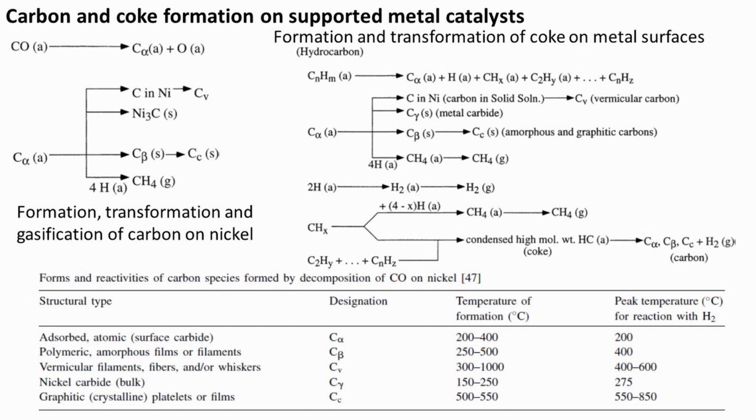The rate at which carbon or coke accumulates in a given reaction under given conditions can vary significantly with catalyst structure, including metal type, metal crystal size, promoters, and catalyst support. For example, supported cobalt, iron, and nickel are active above 350 degrees for filamentous carbon formation from carbon monoxide and hydrocarbons.